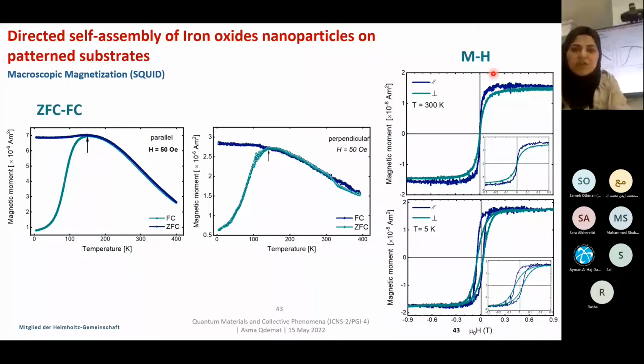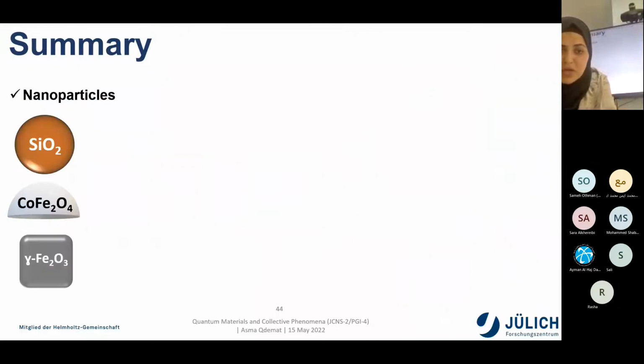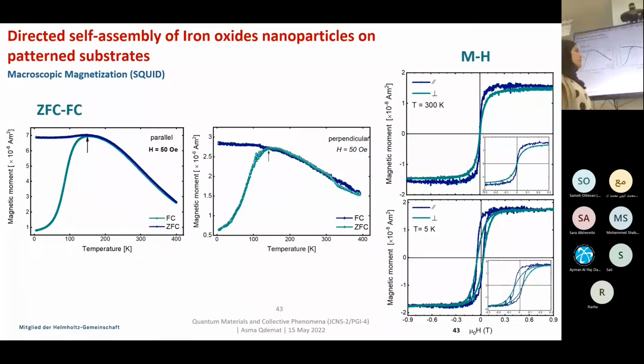For magnetization as a function of the field, in both orientations, parallel and perpendicular, at room temperature we obtained a superparamagnetic behavior, and at low temperature, at 5 Kelvin, both show hysteresis, and also an exchange bias was obtained for the in-plane case, as the hysteresis is shifted toward the negative field. With this part, I would like to emphasize that spatial confinement, meaning directed self-assembly, could be a good approach to improve the order between nanoparticles if the wall width is commensurate with the particle size.